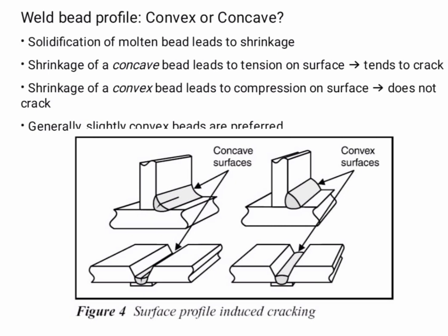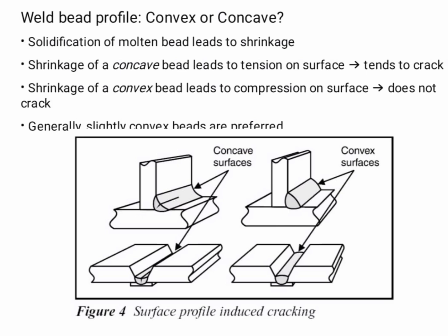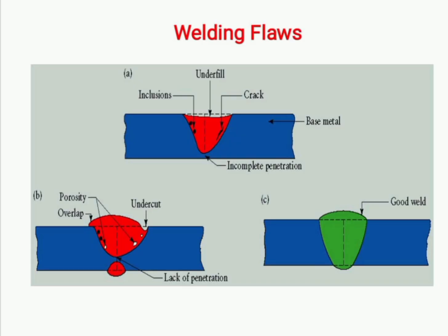Weld bead profile can be convex or concave. Solidification of the molten bead leads to shrinkage, and shrinkage of a concave bead leads to tension on the surface, tending to cracks, while shrinkage of a convex bead leads to compression on the surface and does not crack. Generally, slightly convex beads are preferred. Weld defects and flaws are underfill, inclusions, cracks, incomplete penetration, porosity, overlap, undercut, etc. Incomplete penetration is caused by not enough heat input; you can see on your slide the difference.